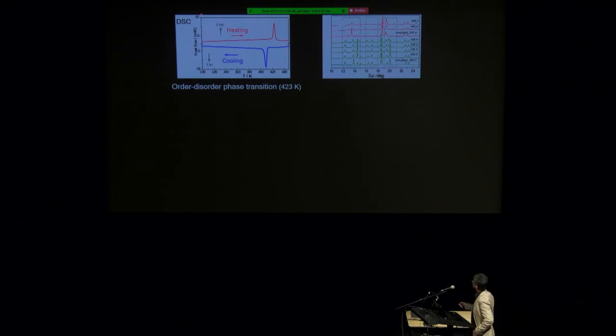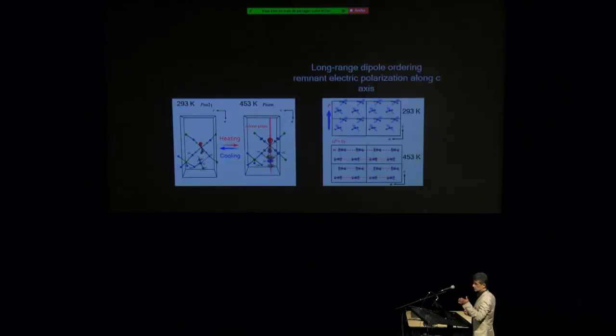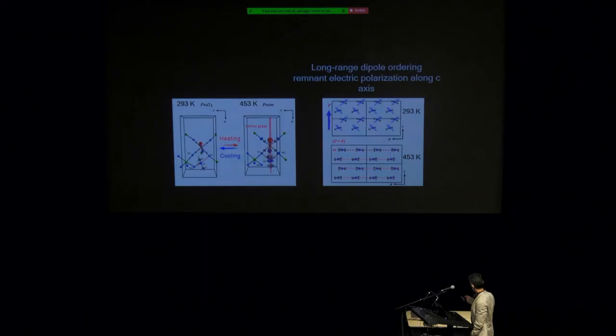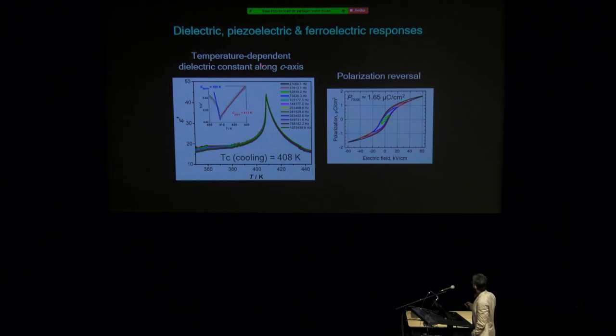Now, these are some of the proofs. DSC does show an order-disorder phase transition at about 423 Kelvin. XRD also shows this phase transition. And then we did single crystal X-ray diffraction, so structure solving at different temperatures, room temperature and higher temperatures. And what we see is that at room temperature, we have long-range dipole ordering and remnant electric polarization along the C-axis, which is destroyed once you go up in temperature, once you go through that DSC peak. So we do have an order-disorder transition, and the starting material is ferroelectric. And if we now measure the dielectric constant at different frequencies and temperatures, that's a typical lambda-type plot you get. And we also study polarization reversal.